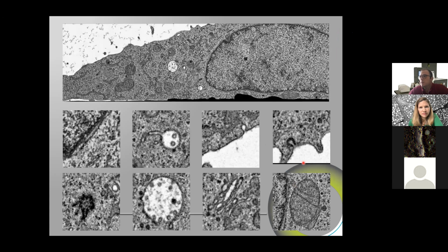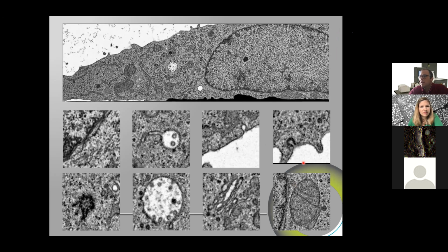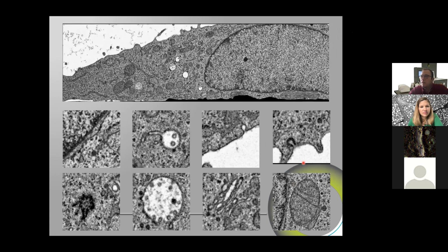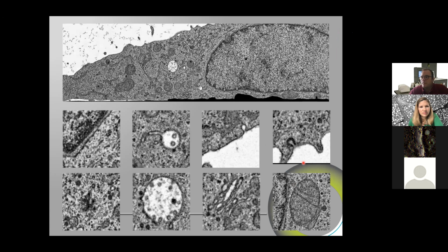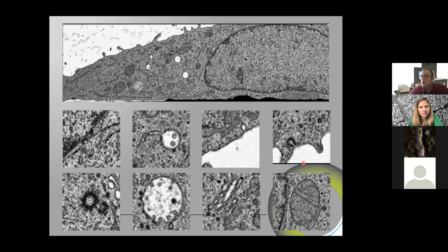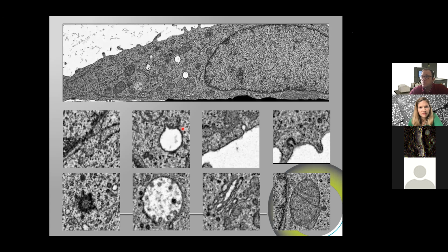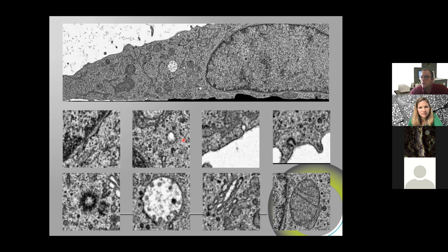I don't know where it's coming from, but it's definitely from the projection. We can see that we can find some very detailed structures. Here we have the mTOC, which is nicely resolved next to the Golgi. We see that the endosomes are nicely presented, and we can see even the coat at the membrane of the endosomes. Also here we see that very well.